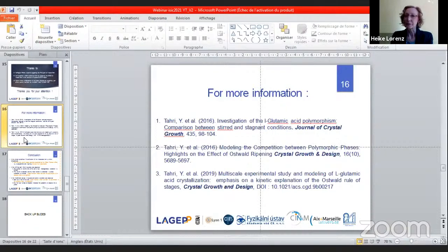In fact, what was the objective of this study when you started? It was to understand why, in some conditions, we couldn't have any clusters of the stable phase, and we had only the metastable phase. We were thinking about it, and we said maybe at some point, in the case of a fast growing metastable phase, we can have small clusters of the stable phase that will become undersaturated and dissolve. But how can we show this? Because experimentally it's difficult. So we tried to do experimentation on different scales, and then to model and to see what happened.